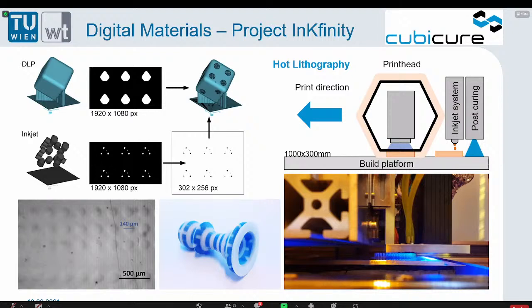Yes, actually, we tried to look at it. It was pretty difficult at that time because we weren't able to distinguish between the ink droplets and the matrix materials, as I said. So we tried different microscopes and tried to see where the crack goes and what actually causes the behavior. Since I left the university, my colleagues tried a lot more and used fluorescence dyes and already showed that the drops have significant influence.